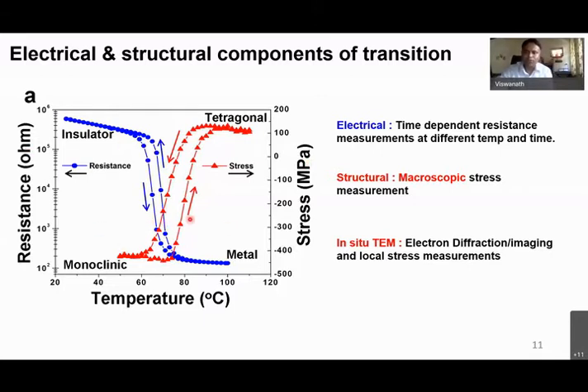In addition to that, we also wanted to cross-check: how do I know there is a phase transformation? I'm saying monoclinic and tetragonal. Of course, we have also done in situ TEM. We can again establish by electron diffraction that there is a phase transformation from monoclinic to tetragonal. For the benefit of time, I'm not getting into the TEM in detail. We also did the imaging, right? There are some contrast changes we can capture during the phase transformation.